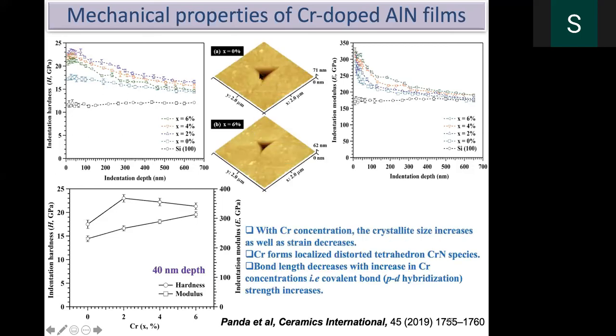Again, if you see the indentation area, the 6% and 0% pure aluminum nitride, this is the addition of chromium. That means with the 6% addition of chromium, the hardness increases compared to that. That's what it shows. From here, it goes up. The error bar shows that the deviation is very, very small.